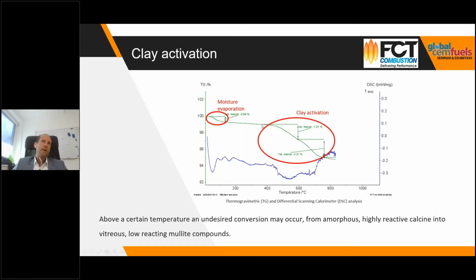Later on, when you continue increasing the temperature of this material, you have another very important reduction in mass, and this is exactly the range of temperatures in which you activate your clay, where you are releasing the hydroxyl from the clay. And if you continue heating this particle, you can see a third change in mass, followed by an exothermic reaction, and this would be the recrystallization of the clay structure. So obviously the moisture evaporation is always here at 100 degrees, but the other two temperatures, for clay activation and recrystallization, depend on each type of clay that you have.